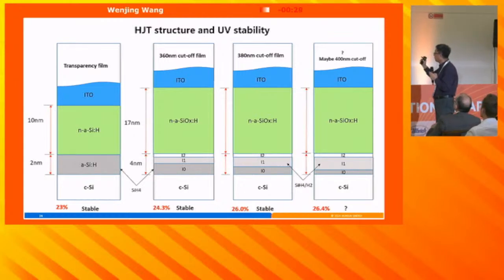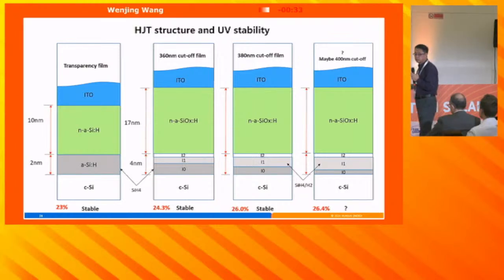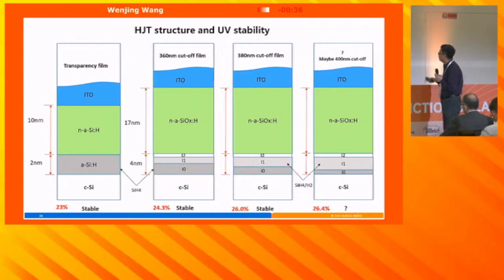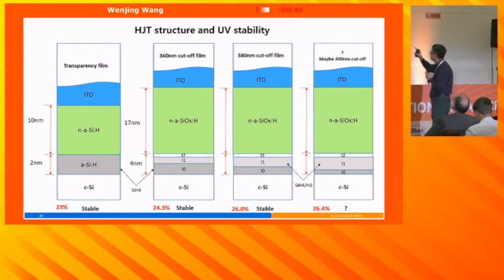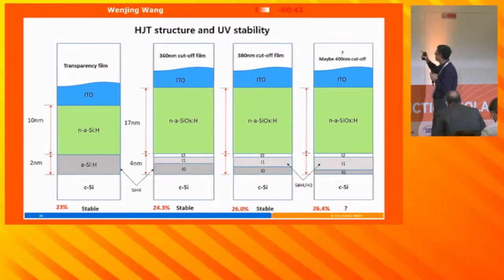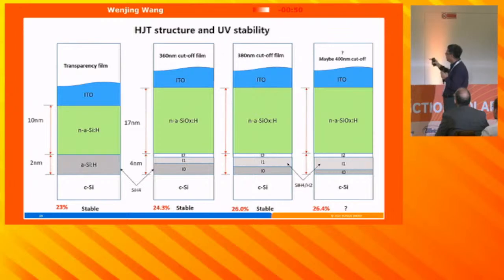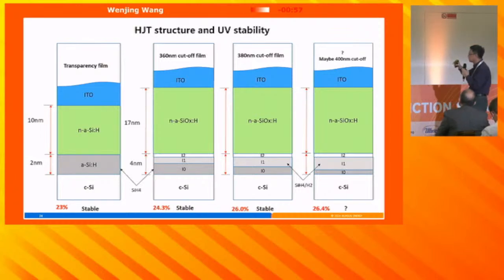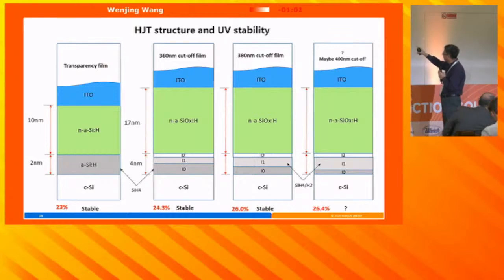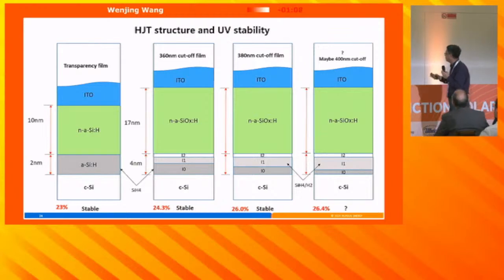totally amorphous silicon thin film, at that time the efficiency was 23%. It's quite stable for UV. But if, for the front side, we use nano-crystalline silicon oxide, more UV light goes inside. And we use a multi-layer of I layer. The thickness of the I layer decreased a little bit. So the efficiency, not only because of this but maybe together with other things, arrived at 24.3%. So there's a UV degradation. So we have to use a 360 nanometer cutoff UV film.